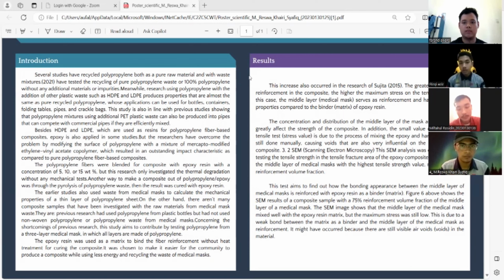Causing voids, which are also very influential on the strength of the composite. 3.2 SEM, or scanning electron microscopy. The SEM analysis was carried out after testing the tensile strength, on the tensile fracture area of the epoxy composite reinforced with the middle layer of medical mask with the highest tensile strength value, namely the 75% reinforcement volume fraction. This test aims to find out how the bonding appearance between the middle layer of medical mask reinforcement and epoxy resin as a binder matrix.